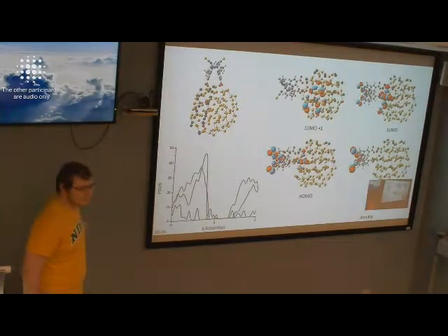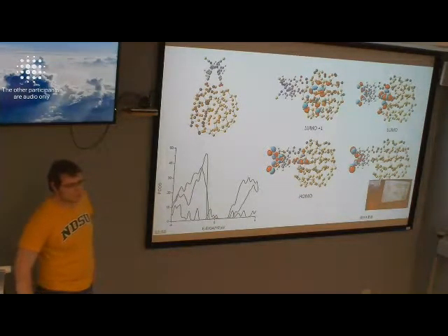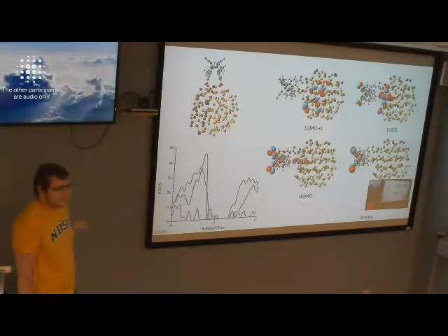If this closed gap is due to the disorder or conformational change of the ligand, is it experimentally feasible for the dye to kick out multiple ligands and take up a large amount of surface on the quantum dot? Or would the ligands that are on the quantum dot when they're synthesized prevent it from doing this? And if it is, could you remedy this by putting a single layer of ligands around it, which then won't let it coordinate to the surface?